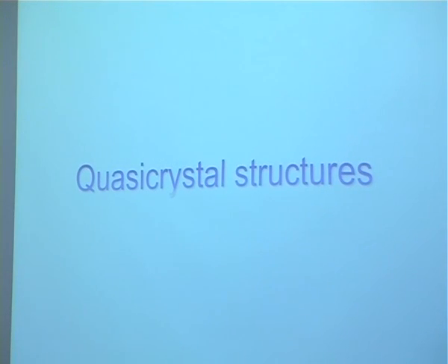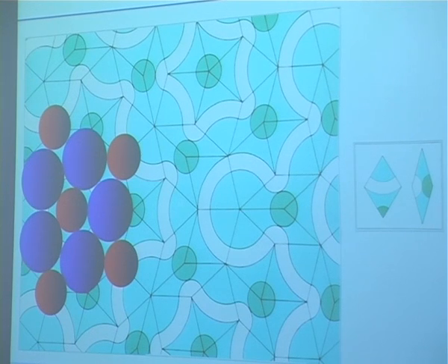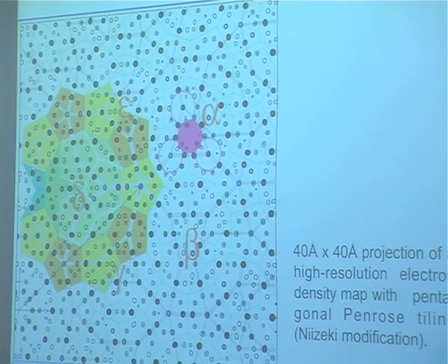And now let's go to quasicrystals. Here we don't have a periodic lattice. We have a quasi-lattice, Penrose tiling, for example. And we can build a model structure just by decorating this quasi-lattice with atoms on the vertices in a proper size ratio. That's one important point. Quasicrystals need atoms to have a proper size ratio. And then we get, for example, a decagonal phase structure. And this is an electron density distribution in decagonal aluminium, nickel, cobalt.